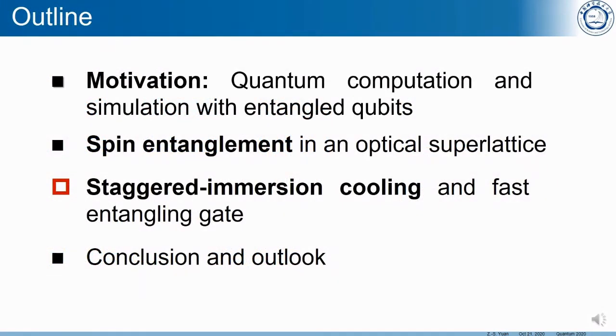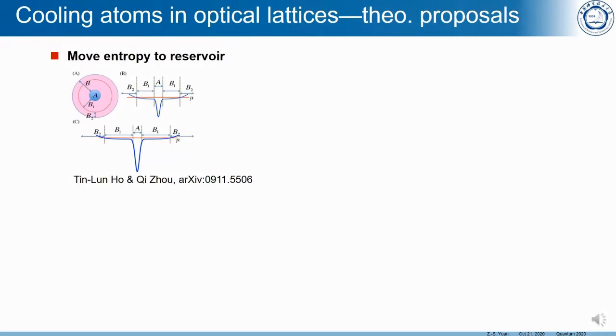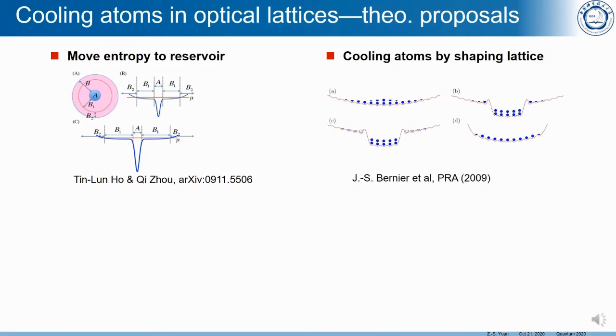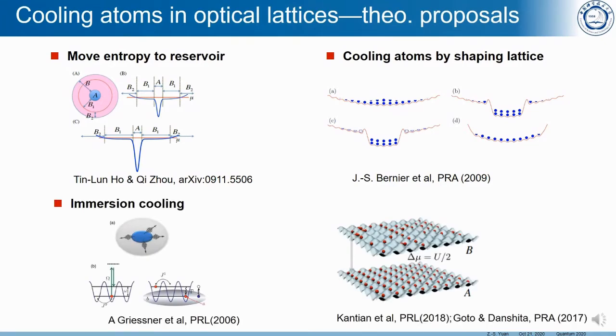Then I will show you our newly developed technique of staggered immersion cooling in the lattice. There have been some theoretical proposals to remove the entropy from the center of the sample to a surrounding reservoir. A similar idea is proposed to reshape the lattice profile for keeping low entropy in the center. One can also immerse an insulator into a fluid. The gapped insulator will be protected from being excited. However, the proposals are really hard to achieve in experiment, or the efficiency of entropy exchange is really low.